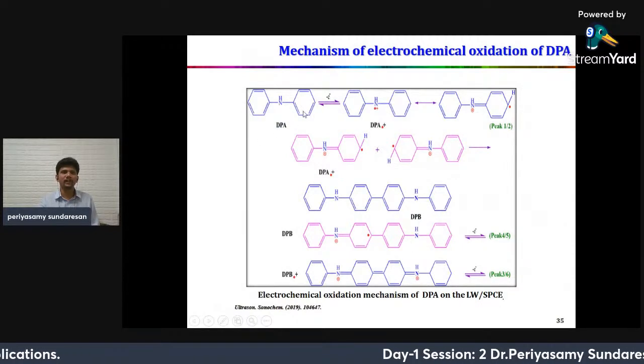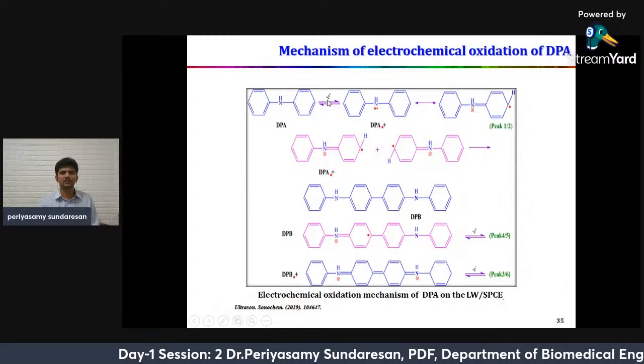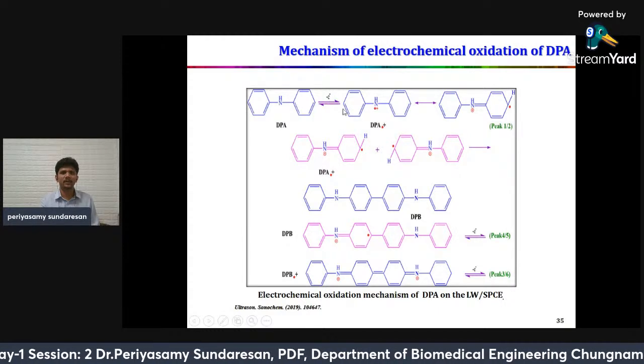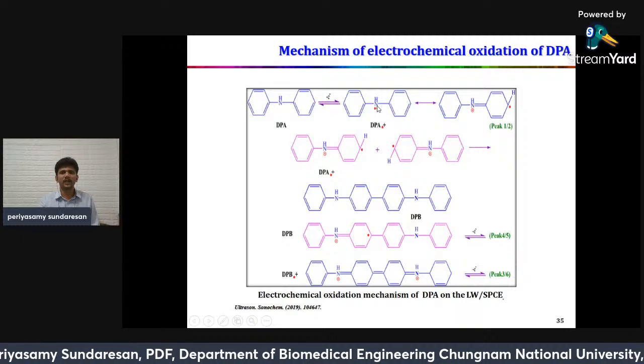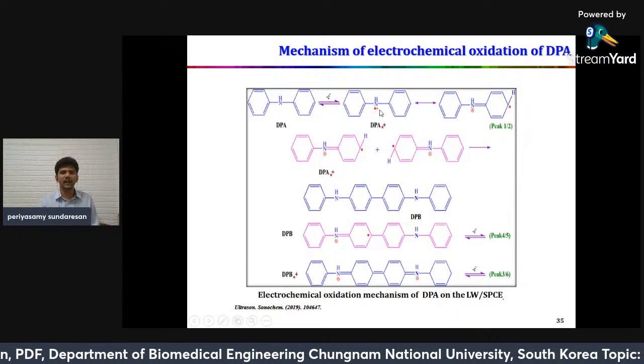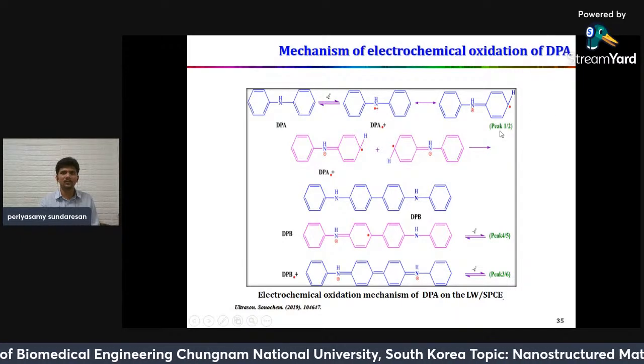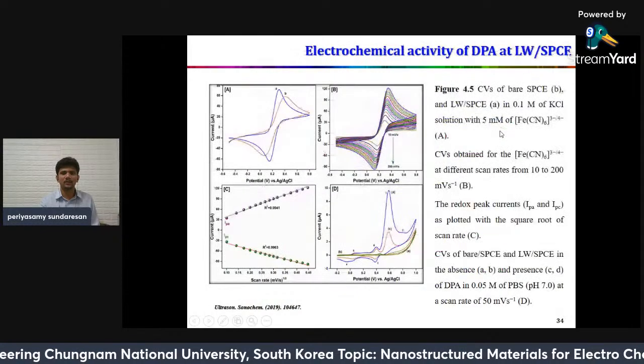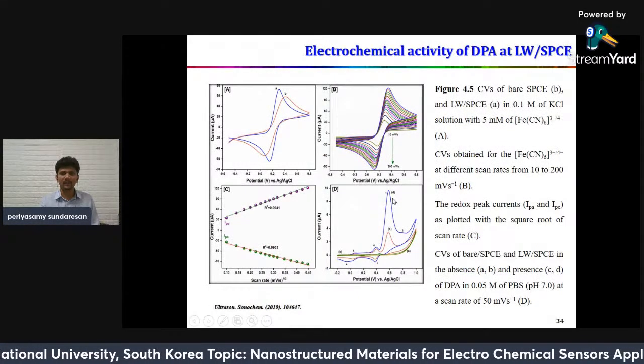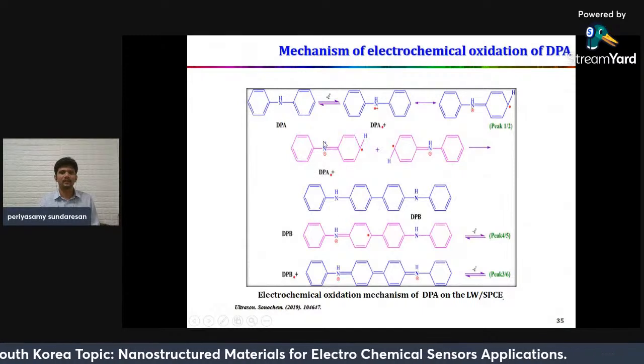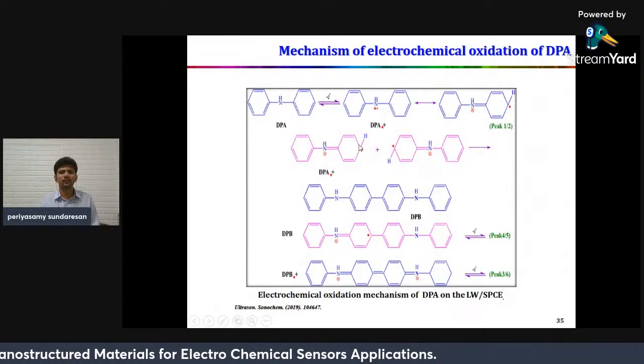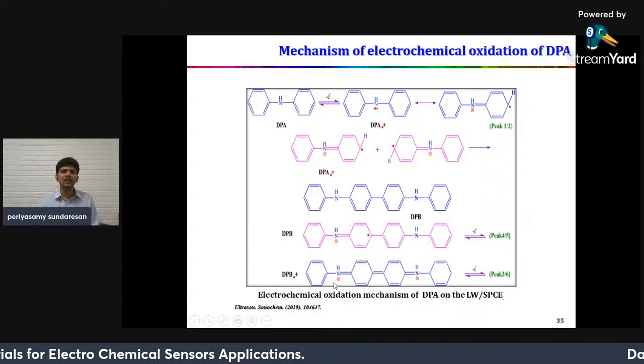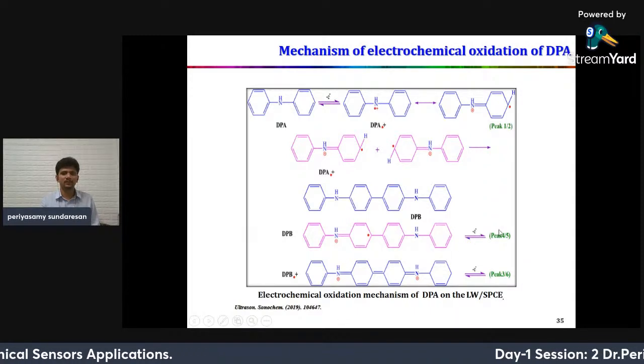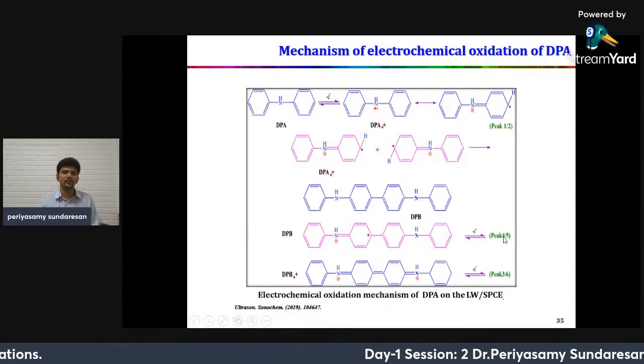This is the diphenylamine structure. Initially, the primary one-electron oxidation appears, so the NH group forms a free radical. This is the major oxidation peak, at 0.6. After that, the group forms a dimer through a dimerization process. Then the dimer gives two peaks: peaks 4 and 5, and peaks 3 and 6.